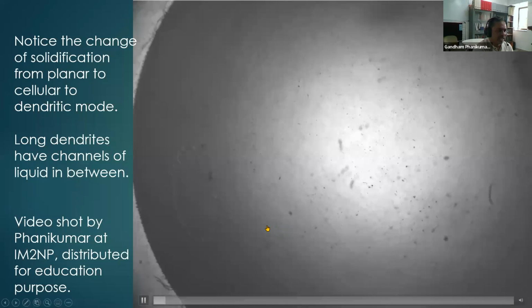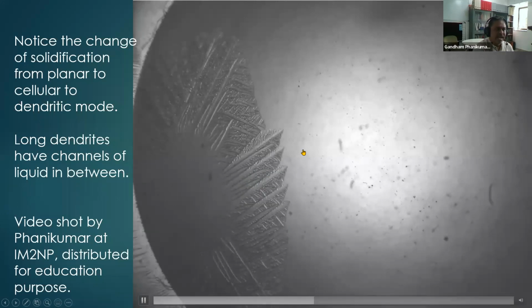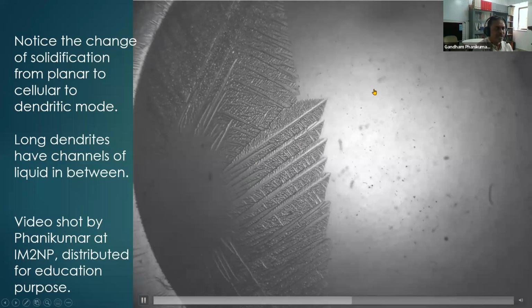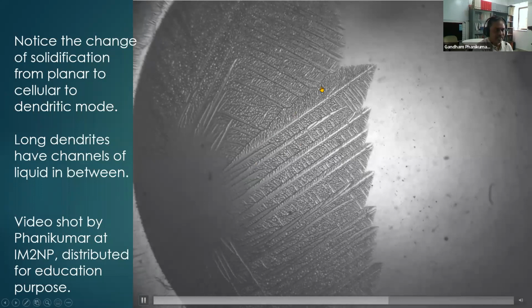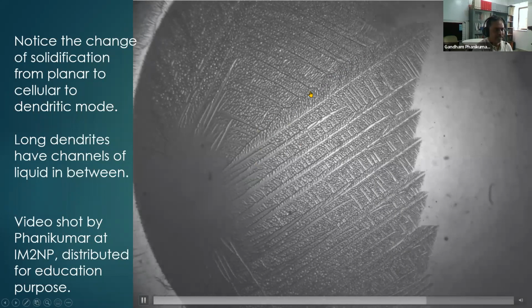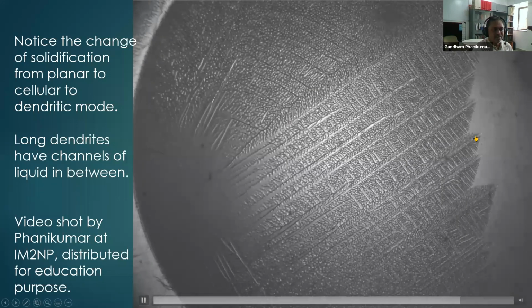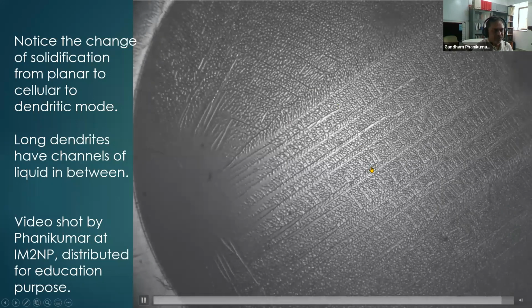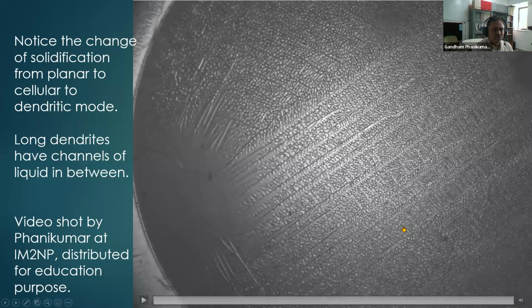Here is a video that you can see: there is a grain of solid and it is growing. As it grows, you can start seeing that the dendrites are forming. And like a tree, they are all growing, and there's a grain boundary that is forming here. So this is a grain boundary. These are all parallel dendrites that are growing, and in between them is the interdendritic liquid, which after finishing the solidification will merge.